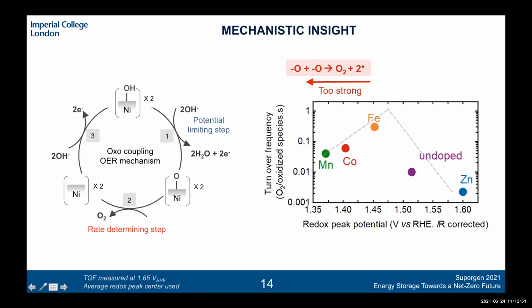On the other hand, on the other leg of the volcano, going from iron to zinc, we know that it takes a huge amount of electrochemical potential to form these oxidized states on the zinc doped site. So in this case, you're basically limited by this potential limiting step of forming these oxo species. And iron is then on the sweet spot of this volcano where it binds oxygen neither too strongly nor weakly, making it a kind of ideal catalyst. So if we wanted to find new catalysts, we're looking basically at this region between the iron doped and the undoped nickel oxide, where we believe that we have more active catalysts in this material space.